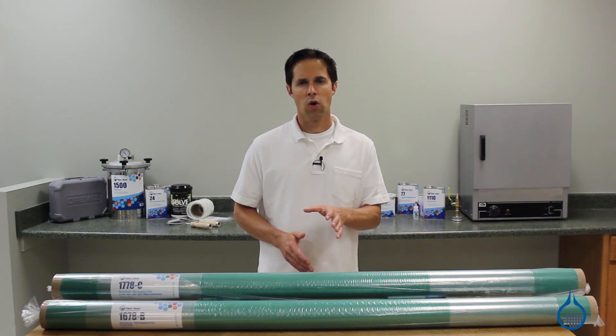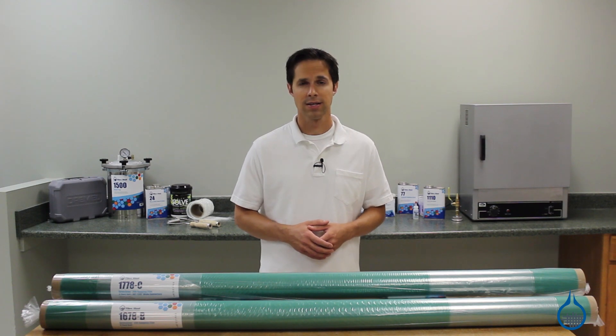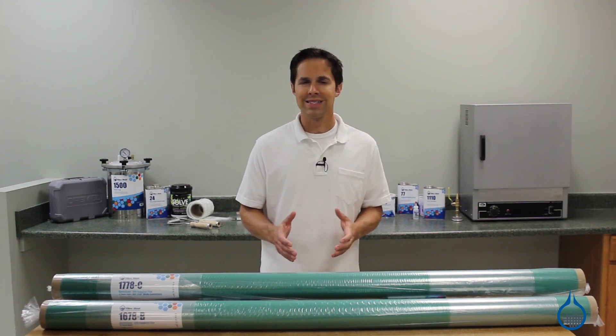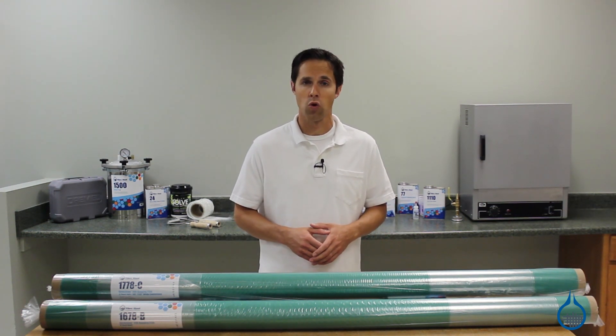Second, Stretchlon 200 should only be used for temperatures that reach a maximum of 250 degrees Fahrenheit. Third, as a thin and stretchy film, Stretchlon 200 is not the most durable material and can develop holes or tears at full stretch over sharp corners. Make sure to cut large enough pieces to not overstretch the film.